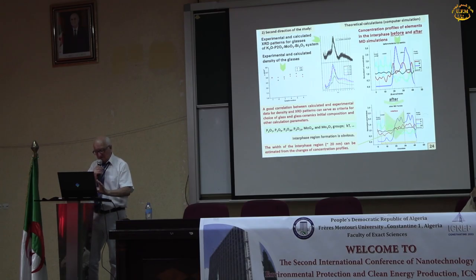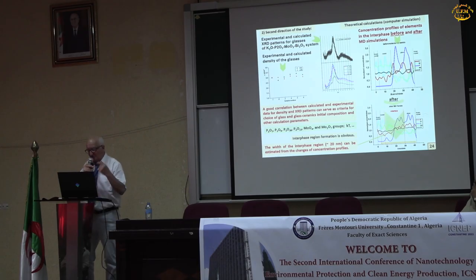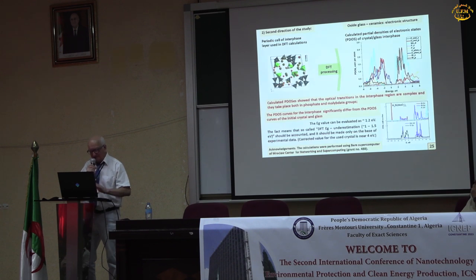We see that this interface layers, and we evaluate the form and large of these interface layers, and we evaluated it as near to 20 nanometer. Then we take the composition of this interface layer for so-called DFT calculation, and we find the electronic structure, partial density of states, and these interface layers, and we can compare this data with experiment.